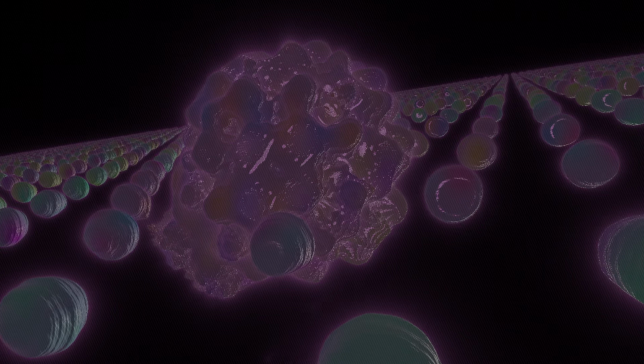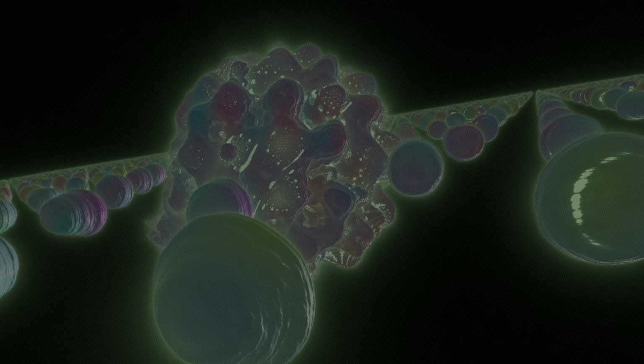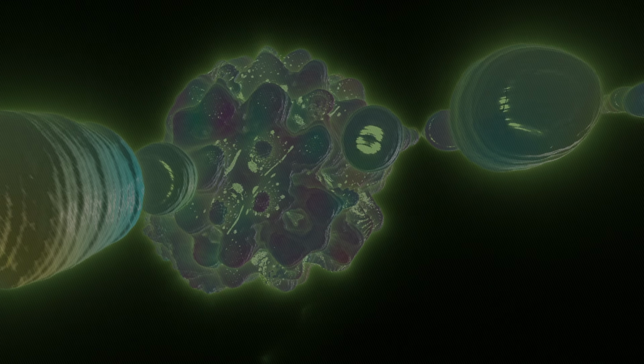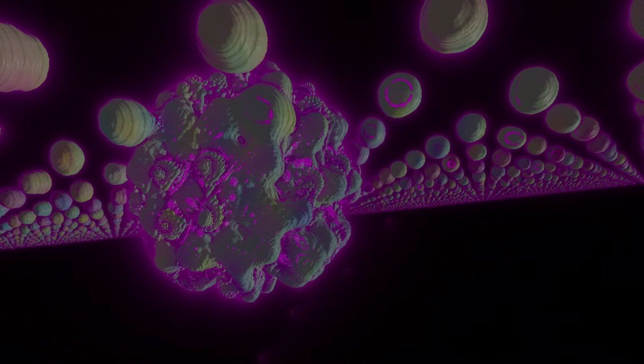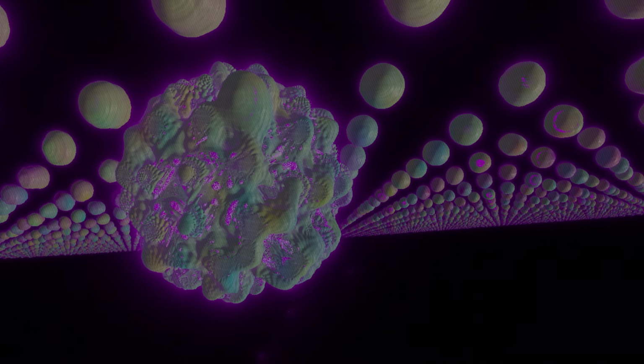What about Brillouin scattering? Brillouin scattering also uses visible light, but it probes the low-frequency acoustic phonons, again near the zone center. It's essentially light diffracting off the periodic density fluctuations created by the sound waves, phonons. It's very useful for measuring elastic constants and the speed of sound directly. There's also a nonlinear version, stimulated Brillouin scattering, SBS, used with intense lasers. So light scattering is good for the zone center, but to map the entire dispersion curve across the whole Brillouin zone, you need something else.